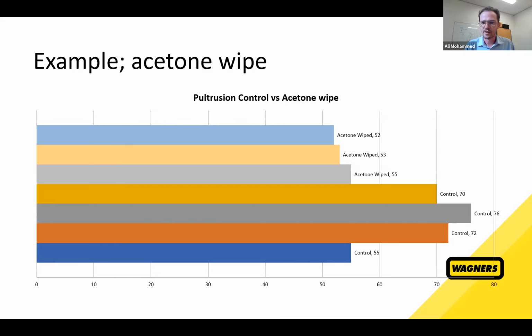For ourselves, we found that wiping, as I've explained, doesn't actually help with our surface energy that much. But here you can see that by acetone wiping our pultrusion, you get a reduction in contact angle. So you could suppose in this test that there was some sort of contaminant on the surface. You go down from 70 degrees or so contact angle to 50 degrees after you acetone wipe. So that's the sort of difference you'd be looking for if you suspected a surface was contaminated. You'd be able to see via measuring that contact angle that the surface is improved after you wipe it.